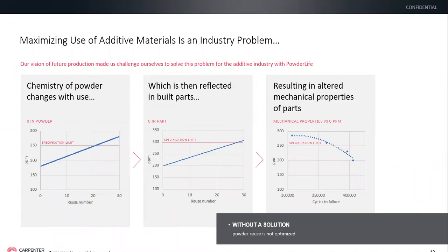A major issue in the field right now is to maximize the use of additive materials. And it's an industry-wide problem. The issue is essentially change in the chemistry of powder with use. As you use your powder in your AM equipment, it leads to nitrogen pickup and oxygen pickup, which changes the chemistry of the powder. And as you keep reusing the powder, the chart on the left shows oxygen pickup. After a certain number of reuse cycles, your oxygen levels in the powder actually are above the specification limit, which, if you still continue to use those powders, is reflected in the parts you build. And that results in variation in mechanical properties of the parts.